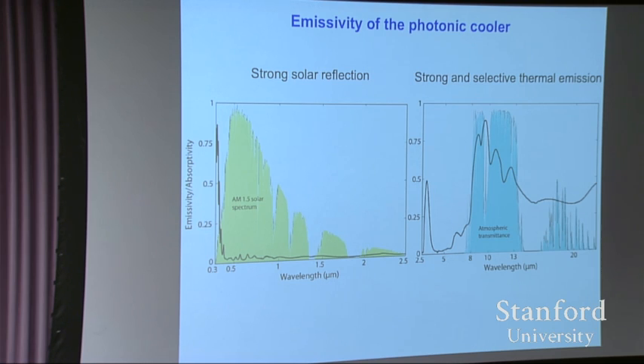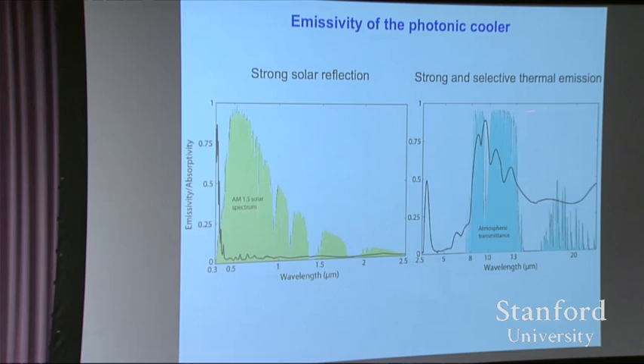So some of the main differences when you come to California from Hawaii, some of the best places, is that the emissivity actually goes down, the transparency goes down in the 8 to 13 micron window. And also the secondary transparency window actually disappeared. So the data that I showed you, if we could do the experiment there, would have been a lot better. Yeah. Okay, all right, yeah.